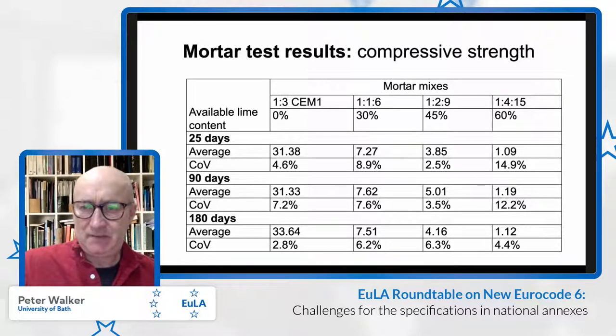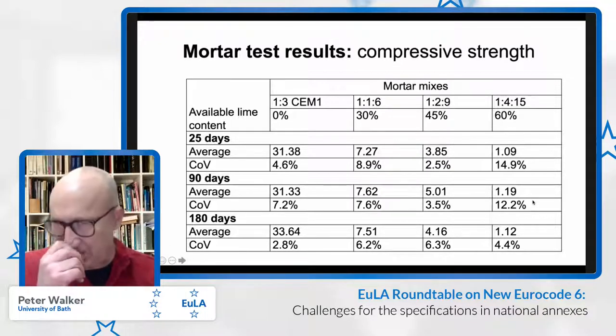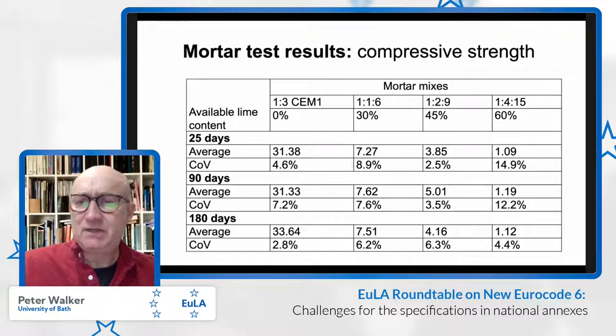What we see here in a general trend is that in each case, the mortars had pretty much attained a great deal of their strength by that first 4 weeks. You can see some increase here in the higher CEM1, and there is some fluctuation here at the 90 days for the 129, and then in the lower strength mix, the 1415, which is a very weak mix and not a generally, widely used material, you've got a compressive strength of just one newton per square millimeter for the mortar.